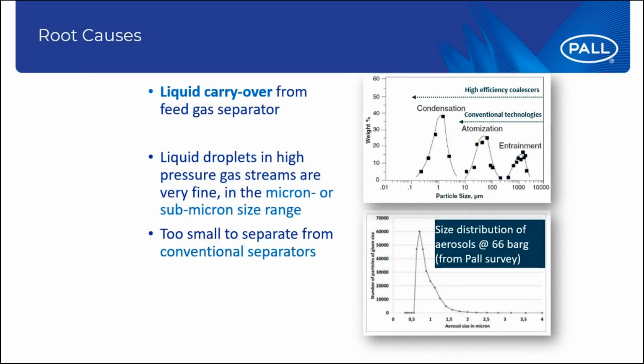And also, as highlighted, the liquid carryover is very fine, and this is justified by a study that shows that liquid droplets in a gas stream, especially at high pressure, exist from three different root causes. They can be reentrained, atomized, or condensed. Usually condensation is one of the highly present phenomena in sour gas, and it generates very fine liquid droplets. We measure them, and it is very important to get them separated by high efficiency separation.